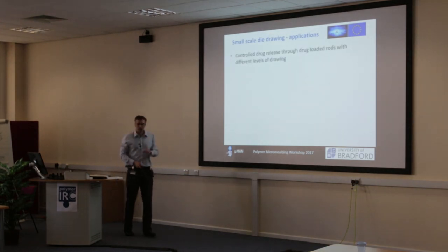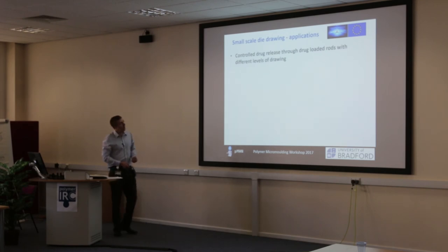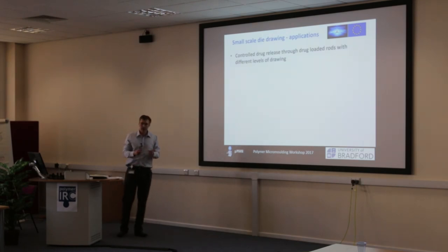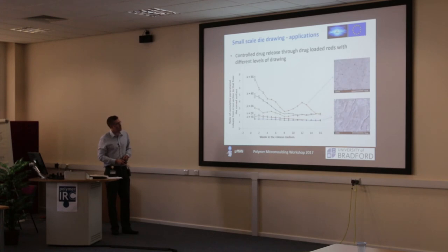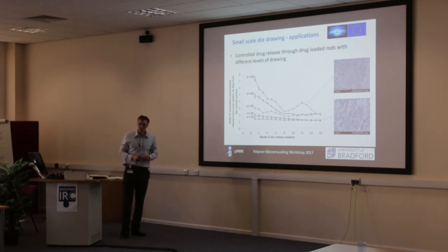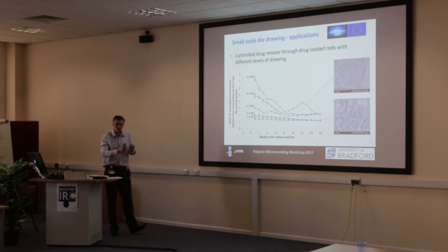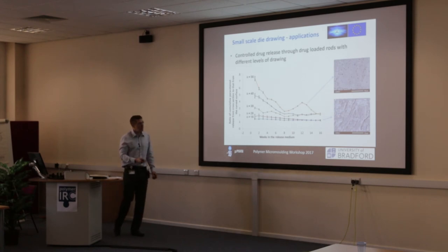And just one final application, going back to pharmaceutical applications and drug delivery, we've looked at how we can tailor the release of drugs by adding orientation into the polymer. So one of the projects we've had was using rods, like the die-drawn rods you were looking at before, but instead of being made from polypropylene, they were made from polylactide, which is a bioresorbable material that can go inside the body, loaded with a drug, drawn to different draw levels. By imparting different draw levels, we could influence the rate of drug release quite significantly. So this is releasing paracetamol over a number of weeks in the dissolution test into the release medium.